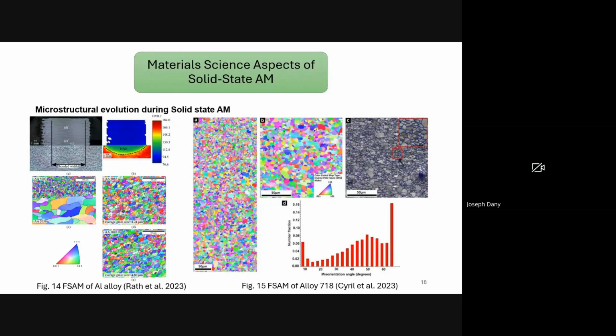The substrate, which is the base material, retains its original coarser grain structure with fewer newly formed high angle grain boundaries because it has experienced little or no severe plastic deformation. By contrast, the deposited, that is processed, region shows a dense population of much finer, equiaxed grains and an increased fraction of high angle grain boundaries, the hallmark of dynamic recrystallization. Intermediate zones, that is the thermomechanically affected zone, or TMAZ, often show elongated or heavily deformed grains with many low angle boundaries, reflecting partial subgrain formation and a progressive boundary rotation towards full recrystallization nearer the deposition region.